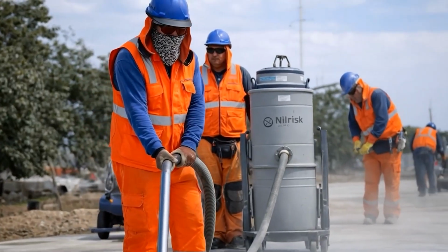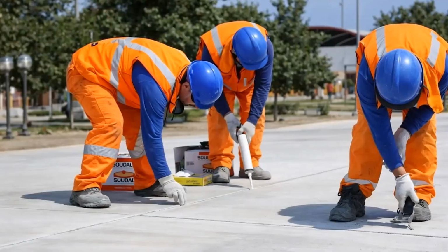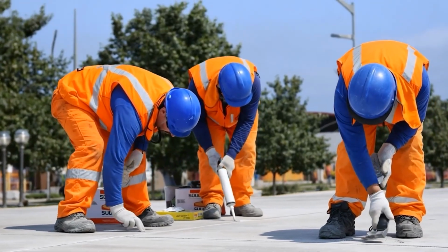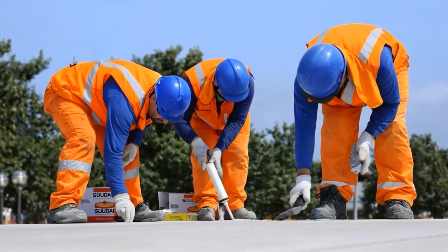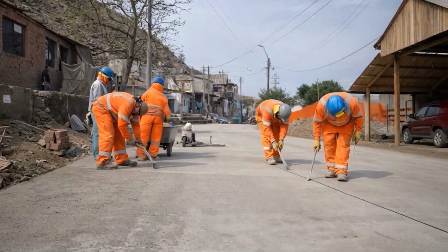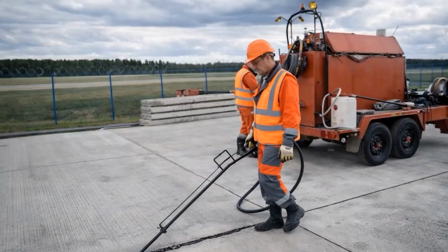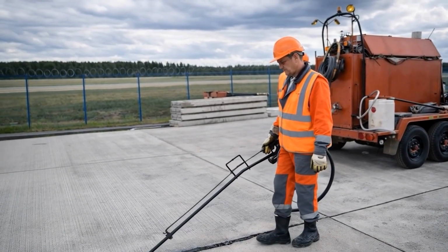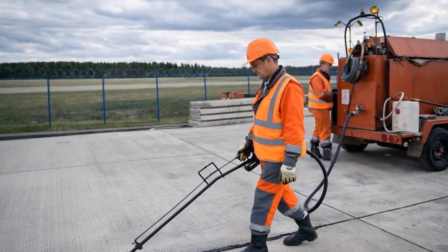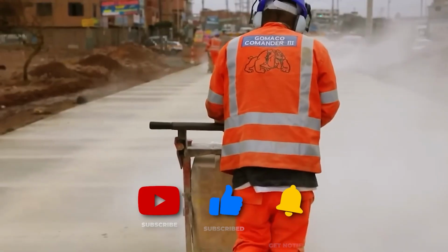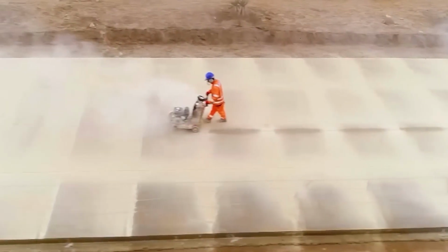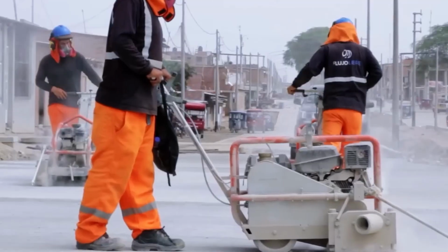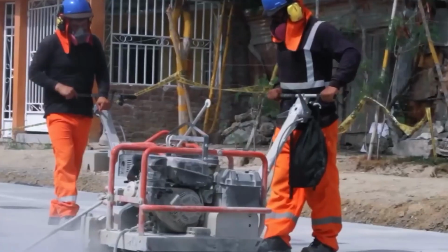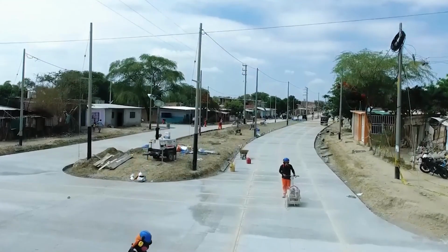Immediately after placement is completed, the entire surface of the fresh concrete is covered with a special liquid curing compound. This layer retains moisture, preventing the concrete from drying out too quickly, and ensures uniform strength gain. After several hours, when the concrete begins to set, workers proceed to cutting deformation joints. Using special saws, straight lines are formed in the pavement at strictly specified intervals. These joints allow the concrete to freely expand and contract with temperature changes without destroying the surface.